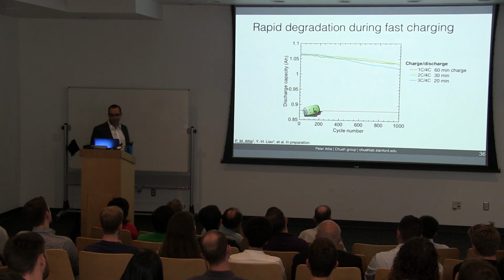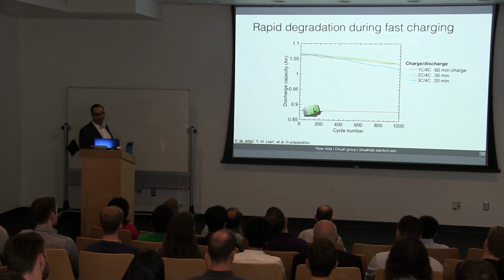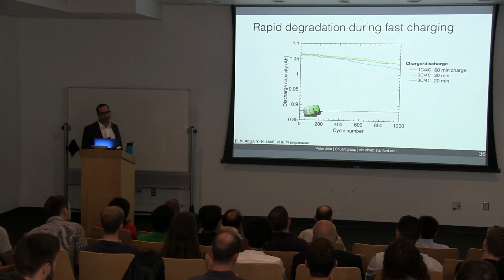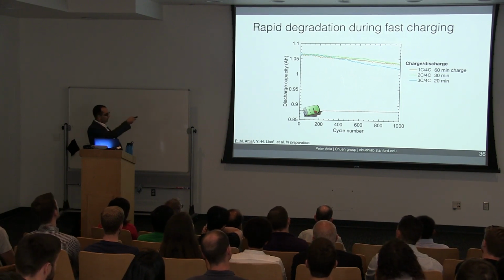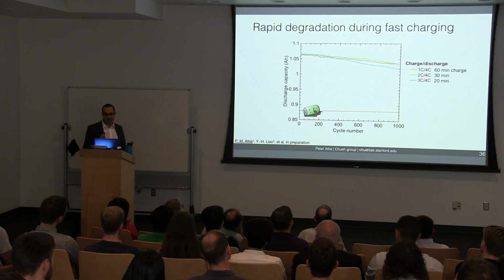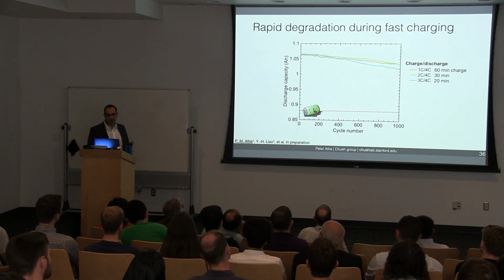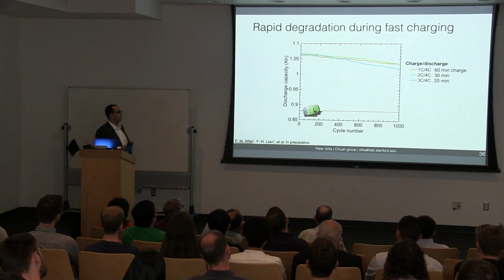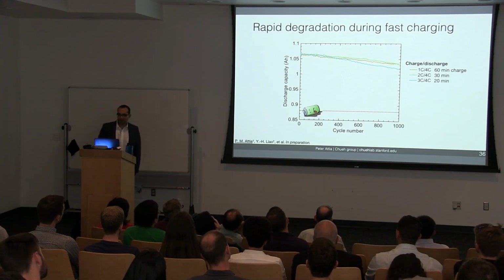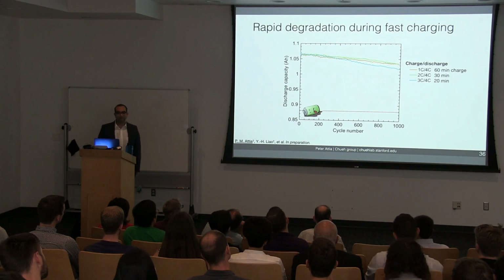Now the goal of this section is to understand degradation during fast charging. In this plot I show discharge capacity versus cycle life. The dotted red line indicates the cycle life. We started by varying the charging rate while keeping the discharging rate fixed. So here we have progressively higher C rates, which correspond to decreasing charging times. So again, 1C is the rate to charge in 1 hour.